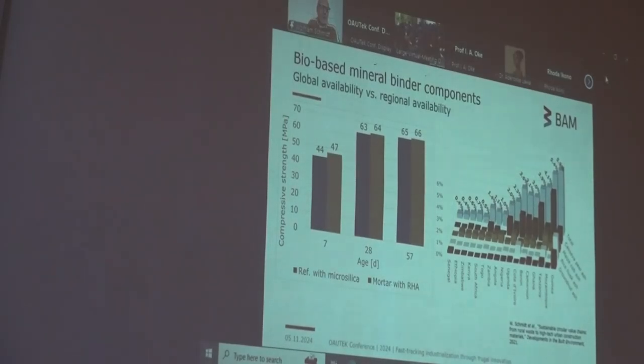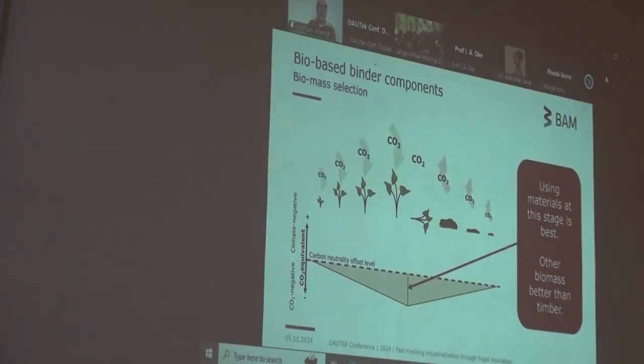This is a performance comparison of industrial mortar using microsilica in blue and using rice husk ash in yellowish. And we can see that the rice husk ash outperforms the microsilica even. And microsilica is very expensive on the global market, and rice husk ashes are wasted, are dumped away. So we have a lot of potentials with cassava, maize cobs, rice husk, groundnut ashes. And that is very important to understand, that these bio-based materials are the real future solution.